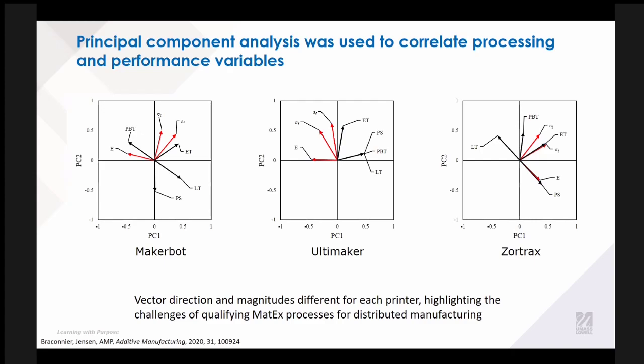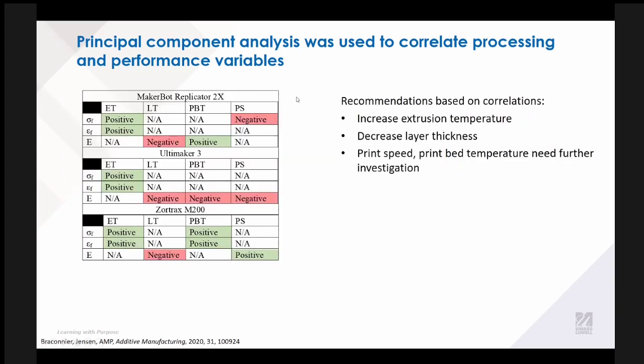Then we have our inputs in black and our outputs in red. And at a really high level, what you can say is these plots don't look anything like each other. We can get into a little bit more detail. We do see that in all cases there was a positive correlation with extruder temperature. We see that there was a negative correlation between layer thickness and our Young's modulus. So having higher layer thicknesses reduces our Young's modulus.